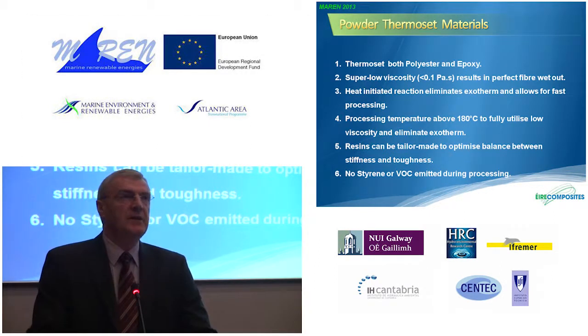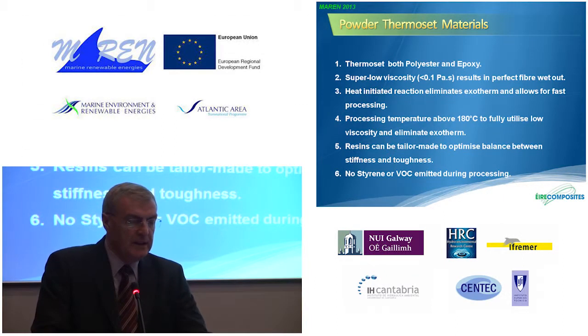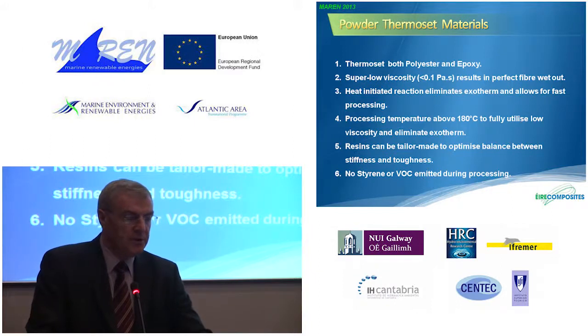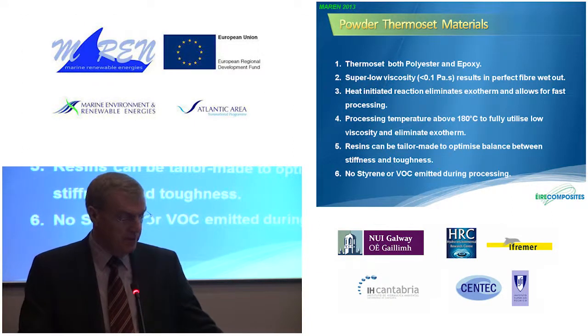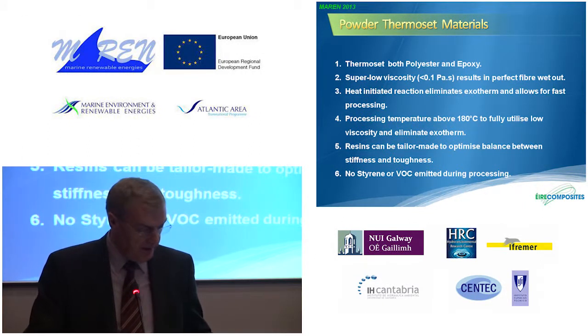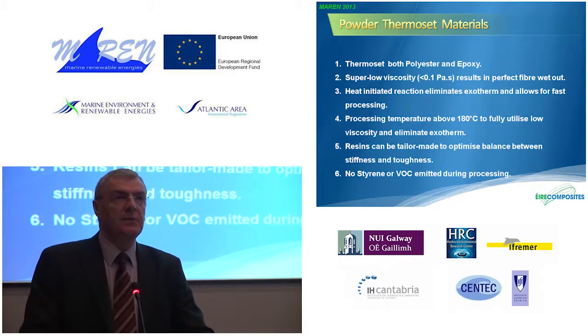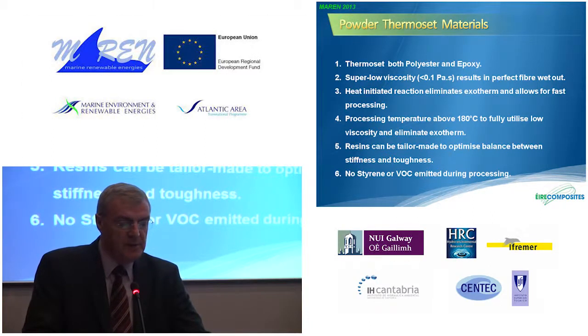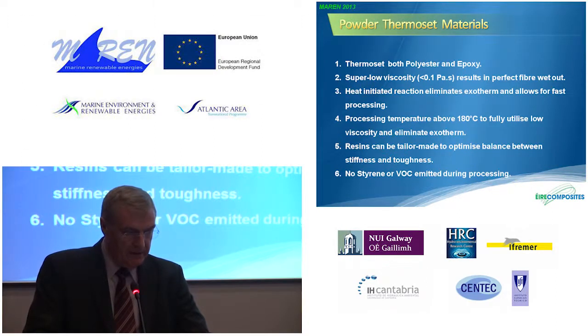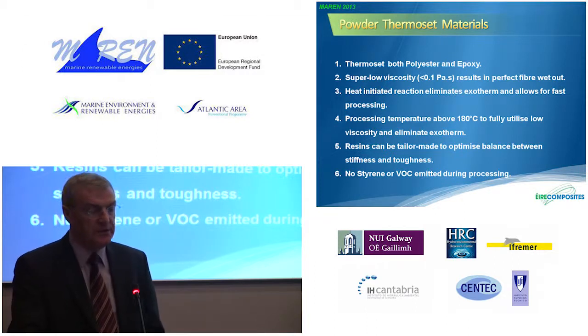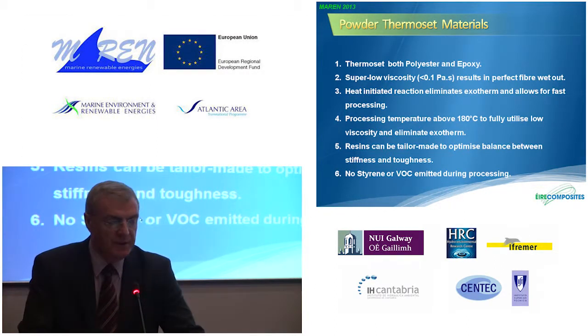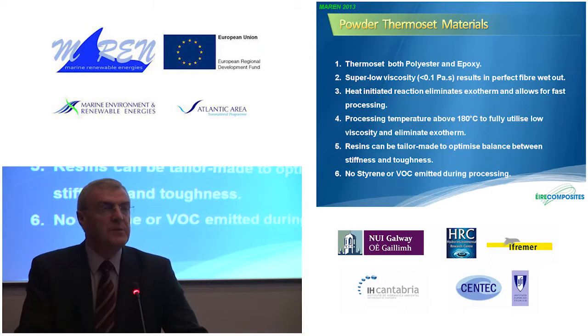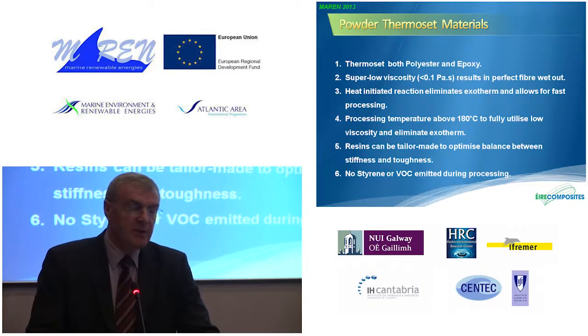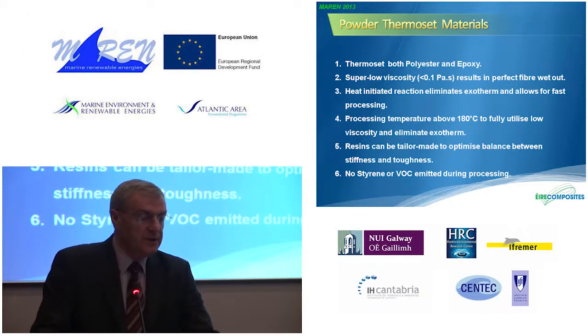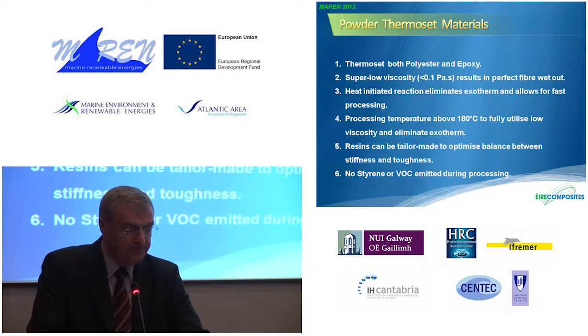They have a lot of advantages over standard liquid epoxies and polyesters in that they are solid at room temperature, so they are easy to handle. They don't require any special storage in your factory, and therefore they're also more environmentally friendly to process. When you heat them to their processing temperature, they go to a very low viscosity, which means you can wet out the fibres perfectly. The heat-initiated reaction rather than chemical means that you can process them faster, even if you're processing very thick sections. Once you get above the processing temperature of 180 degrees, you can achieve the very low viscosity, and also you eliminate the exotherm.